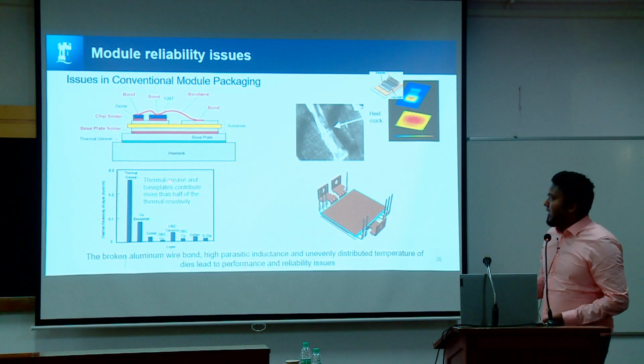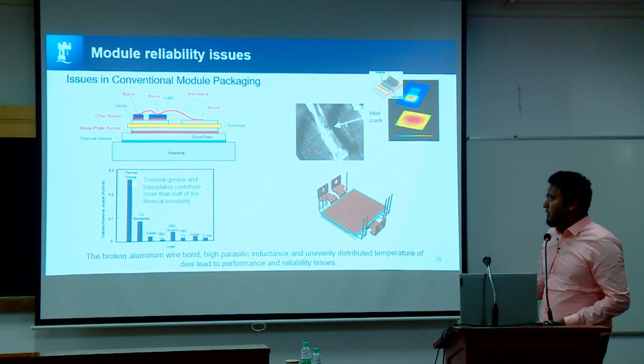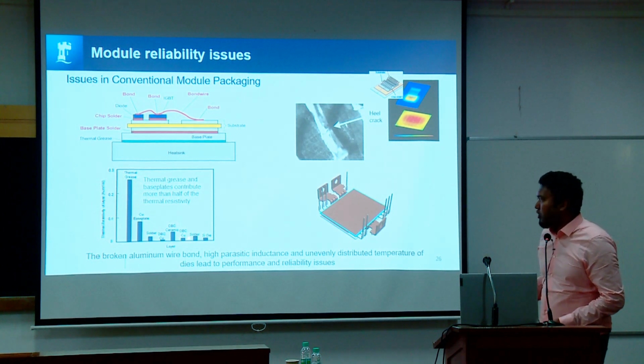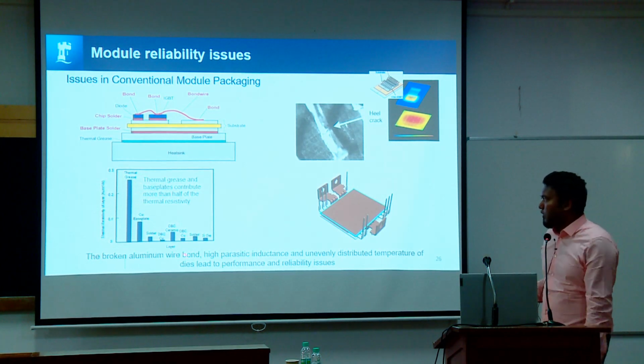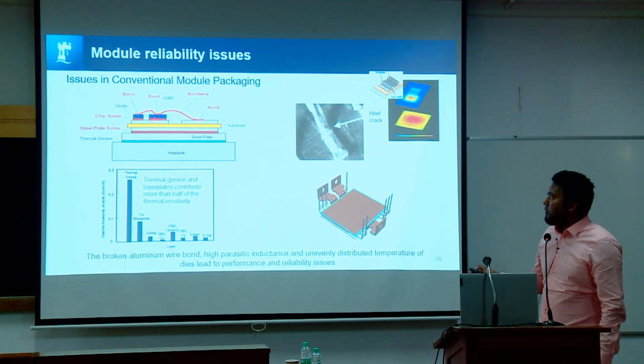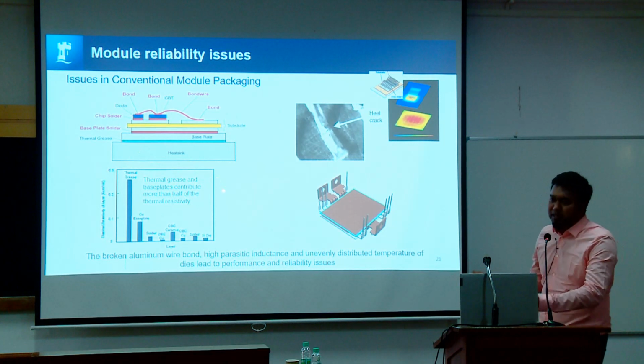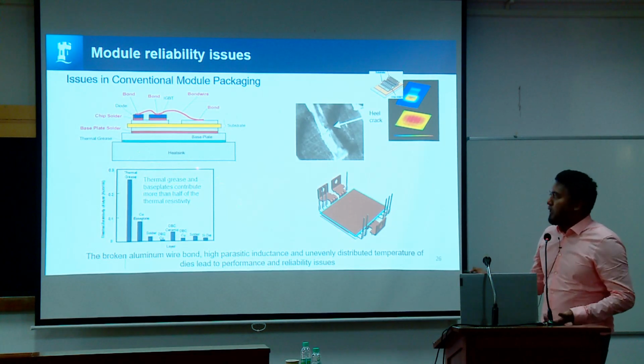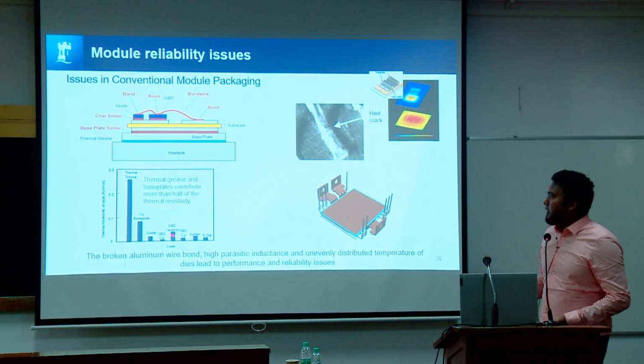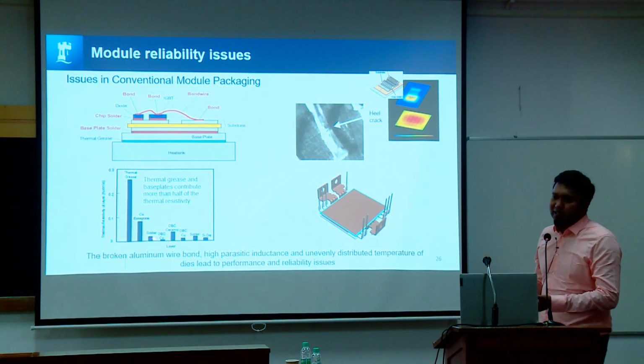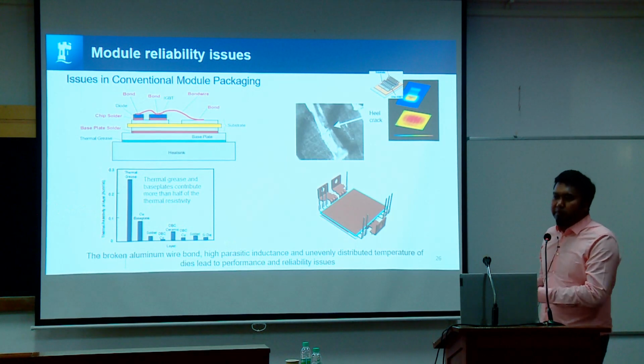Now, if we look at the thermal properties of these different layers, as you can see, they have different resistivity. Thermal grease has the highest, and then obviously silicon die or copper, they have the lowest thermal resistivity. So getting the heat out from the die to the heat sink to the cooling material, which can be a liquid coolant, obviously it's challenging.